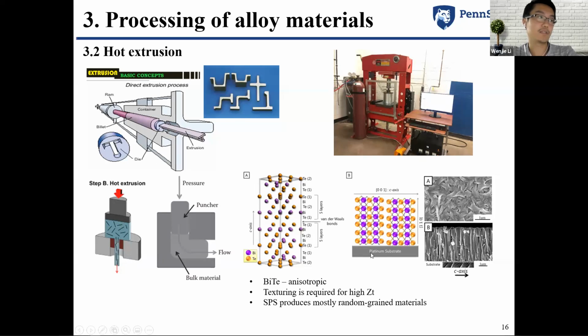We can improve the ZT by 20 to 30%. And not only this type of extrusion, people are also trying different types of extrusion, like this one, because they want to generate more defects or dislocations inside the thermoelectric materials as an additional phonon scattering source to lower the thermal conductivity.